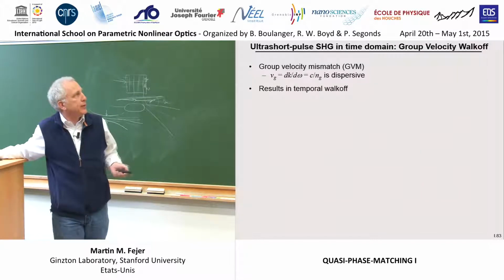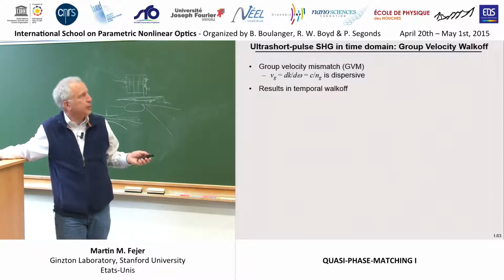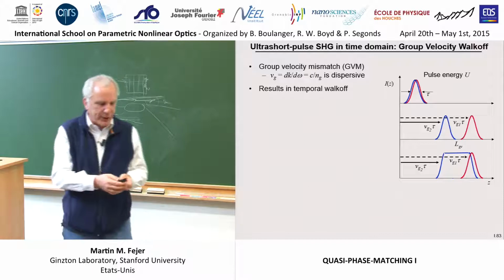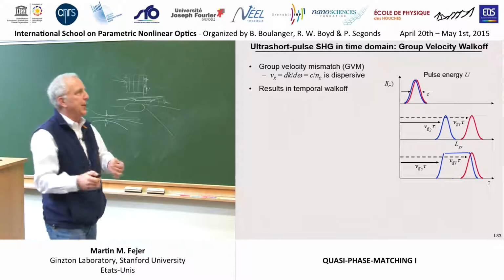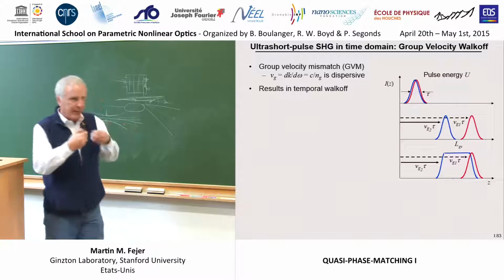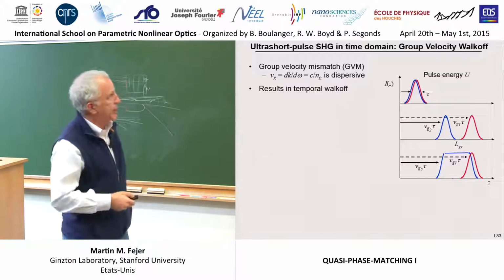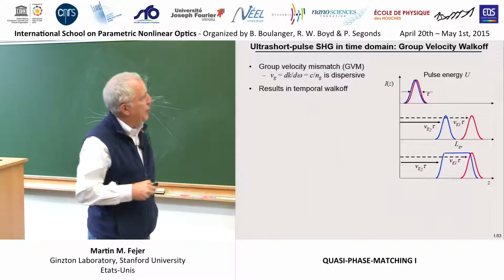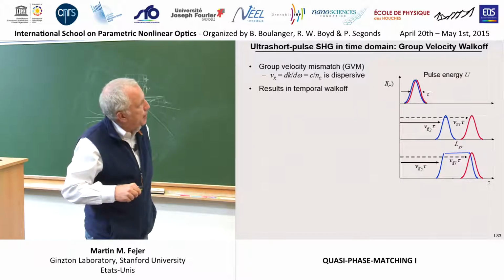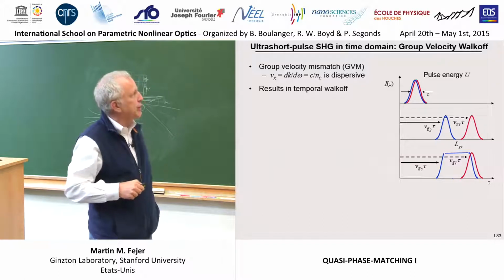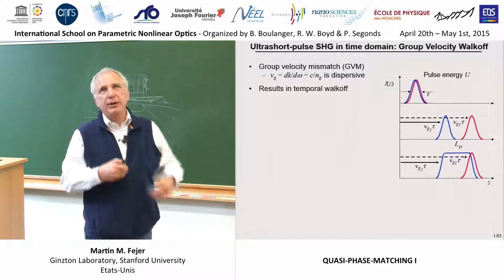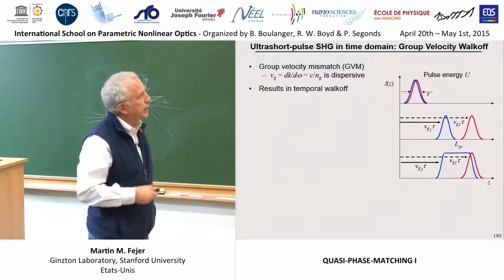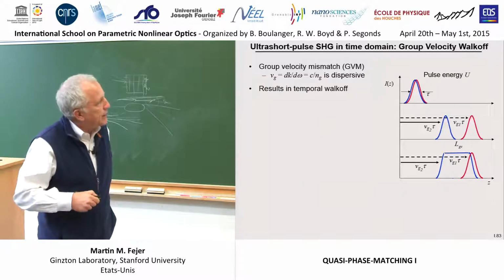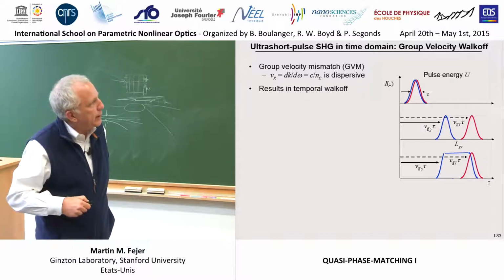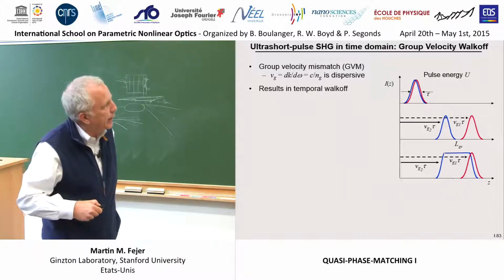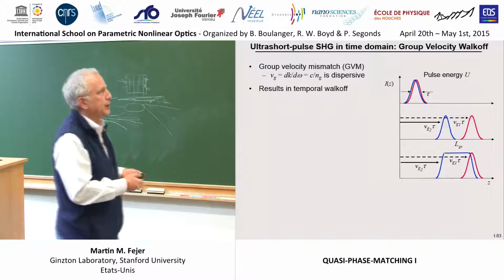In general, the group velocity is dispersive, and that leads to group velocity mismatch between, say, the pump and the harmonic wave in a second harmonic generation experiment, and results in temporal walk-off. In other words, imagine I put in a pulse, a red pulse of some duration tau, and it makes a contribution to the second harmonic, which is also of a similar duration. And then as these things move through the crystal, the red light is moving with its group velocity, the blue light is moving with a different group velocity, typically slower.